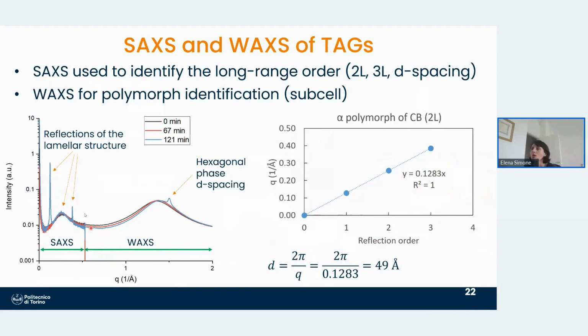And these are some examples of polymorphs of TAGs. This is the SAXS region and the WAXS region of an alpha polymorph. A hexagonal subcell has only one peak in the WAXS region. And then in the SAXS region, we can see a series of equally spaced peaks. If we plot their position, the scattering vector as a function of the order of reflection, we get a line, and the slope of this line is exactly that d-spacing. So how big is the lamella of our structure? So this is an alpha polymorph.